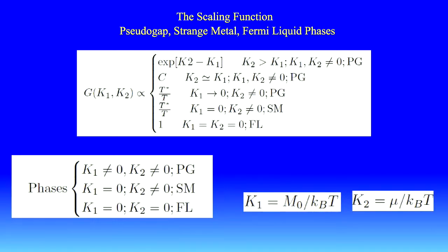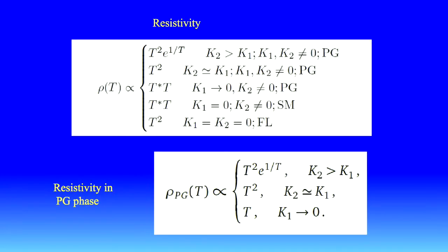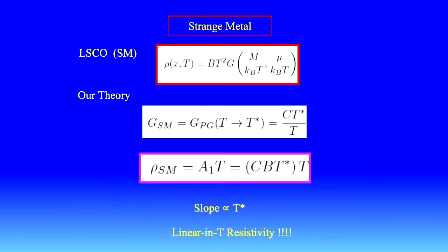So this is the value of each of these functions in the different phases: pseudo gap, strange metal and Fermi liquid. And if you plug this in the resistivity, we have these expressions here. Now, in strange metal, we have this expression for G, which leads very naturally to the linear dependent resistivity without having to make any fancy assumptions about Planckian times and such things. And we predict that the slope is proportional to the pseudo gap temperature.